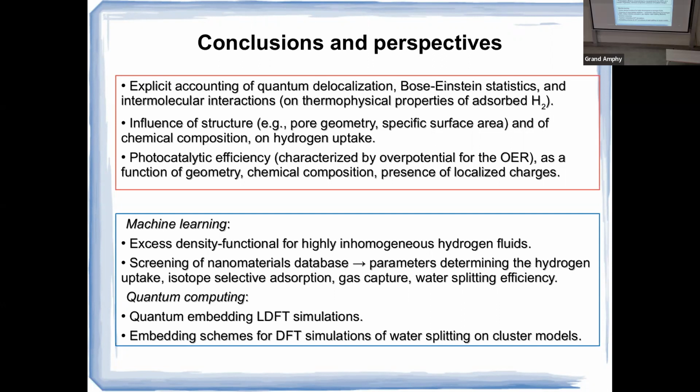So in our calculations of hydrogen storage, we have found, for example, that many times we have noticeable quantum effects at pressures and temperatures where they are completely absent for the homogeneous fluid, because of the confinement posed by the nanostructure. So sometimes it's desirable to have a reference that is not so biased toward these homogeneous ansatz. We don't have access to that.